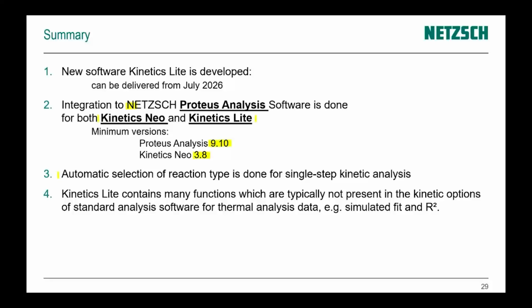Now we have automatic selection of reaction type for single-step kinetics, again for both Kinetics Neo and Kinetics Lite. And additionally, Kinetics Lite contains many functions which are typically not present in kinetic options of a standard analysis software for thermal analysis. So if you take alternative standard analysis software, then usually there is no simulated fit and no R-squared. And if it is not present, then there is some problem to see if this kinetics are really correct or not.